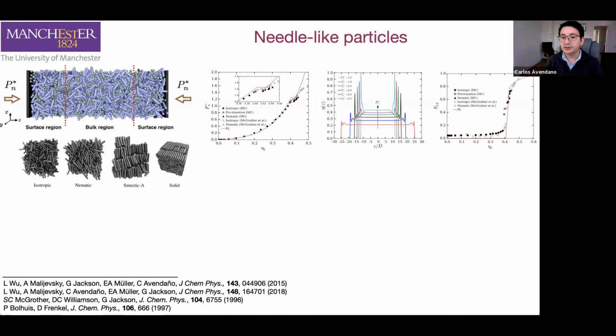So that was a problem because we wanted to obtain the phase behavior, but we knew that the technique wasn't working. So what we decided, and there was an idea from George and Eric, is maybe we can confine the particles between two walls. That will create enough surface tension for the system. And then we can analyze what happens in the middle of the sample. The system still will have a chance to segregate or change in composition along this direction, but at least the system will be stable now. So we decided to use geometrical confinement as a tool to study the phase diagram of these systems. And these are the results.